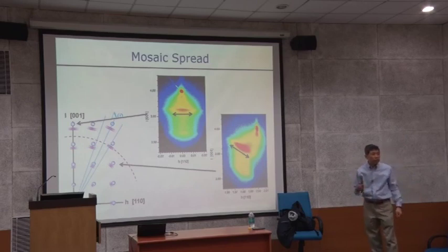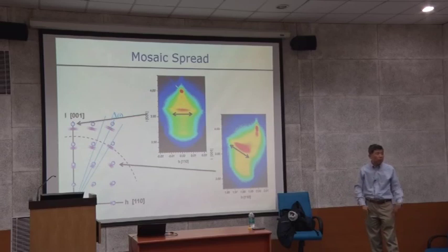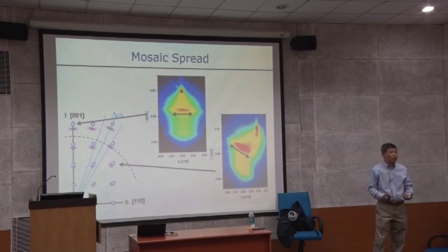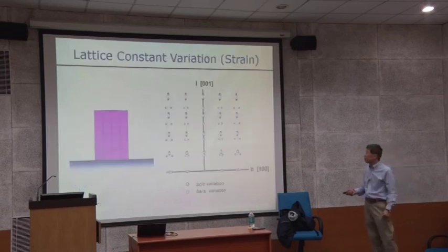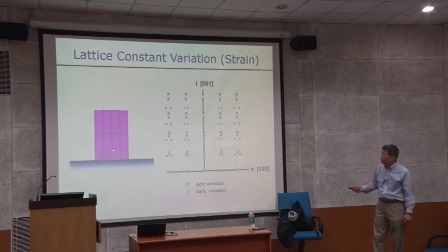So for most of your X-ray diffraction, your thin films on a single crystal substrate give a very sharp and narrow peak. But your thin films show broadening in both directions. And the broadening is contributed by different factors. It's size or crystalline quality or strain, all this information is coming from there. Okay, that is the constant variation, as I said. You have the exact information: you have this lattice parameter small, medium, and large.